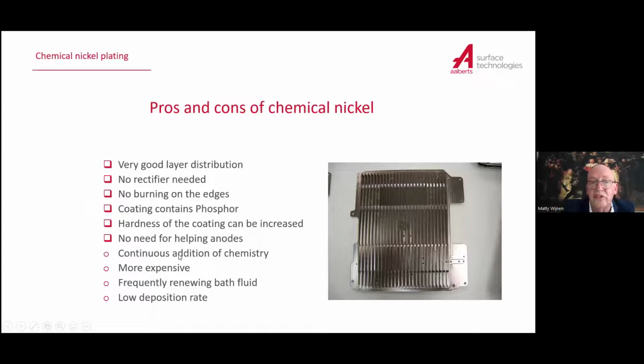Disadvantages are that you have to continuously add chemistry, because you don't dissolve any anode, so you have to put in your nickel and your hypophosphite, your reduction agent, continuously. Your bath has a limited lifetime. You can't work 25 years with the same bath. After, say, 2 or 3 weeks or 2 or 3 months, you have to renew the bath completely. So that, together with the addition of chemistry, makes it a much more expensive process than the electrolytic process. And it has a really low deposition rate. We talk about, say, max 20 microns an hour, but normal standard is just about 12 microns an hour.